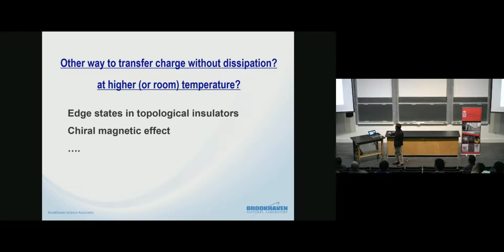It turns out the edge state in topological insulators is one possible way to transfer charge without resistance, because those states are protected by topology and backward scattering is limited. Sometimes it's totally blocked. However, if you have a bulk insulator, the edge on the surface is conducting, but the cross section is not that large, right? If you want to transfer a massive amount of current, it's difficult to do just from the edge or surface. You want to have a bulk, right?